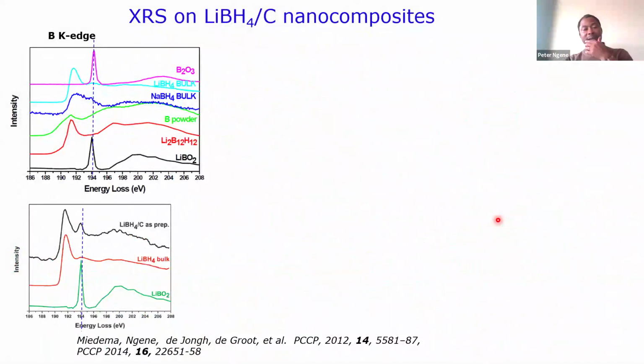So we wanted to figure out what exactly is this peak at this 194 eV. And so we did fingerprinting, because even the calculation at that time was not well developed. So we started with all kinds of different boron-based compounds for the boron K edge, because the boron spectra was much better compared to the lithium. So what we see here are different reference compounds, including sodium borohydride, and these are the compounds that we can think, okay, it could be part of the decomposition product, like this particular compound and boron.